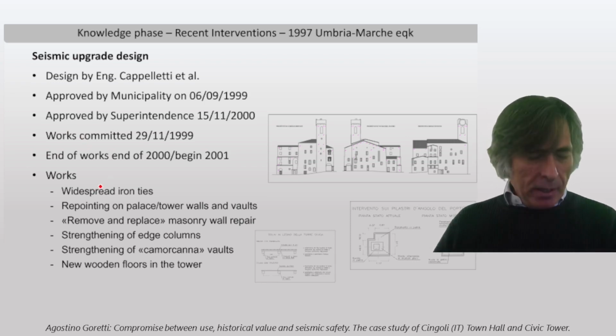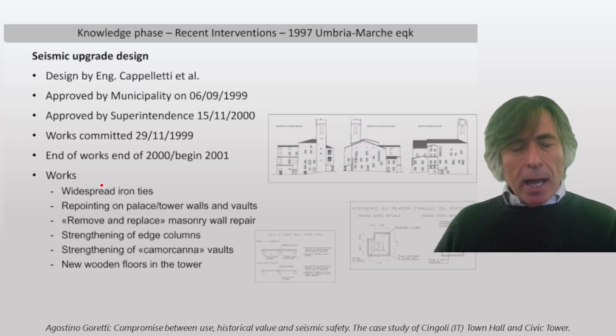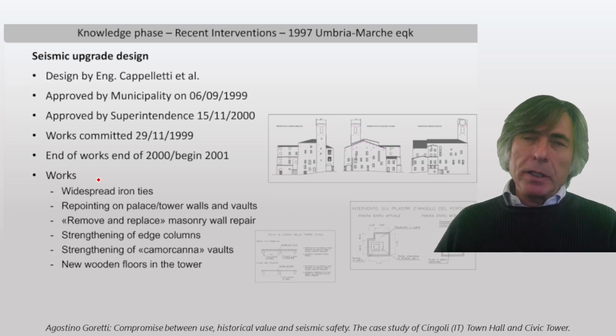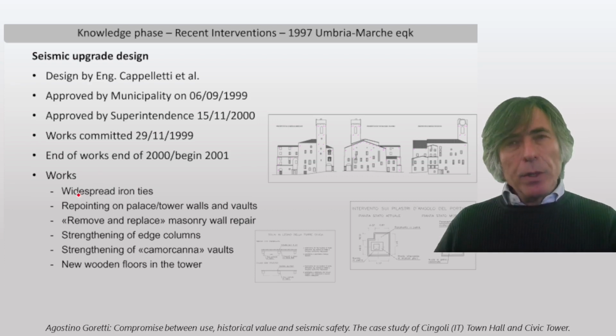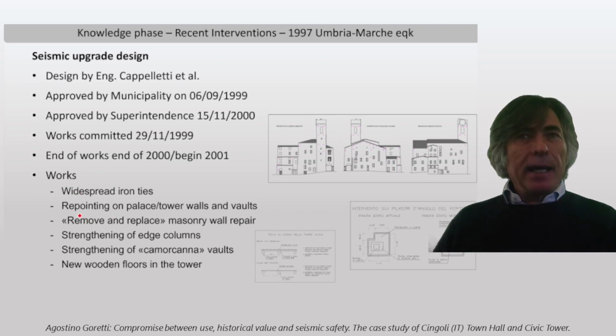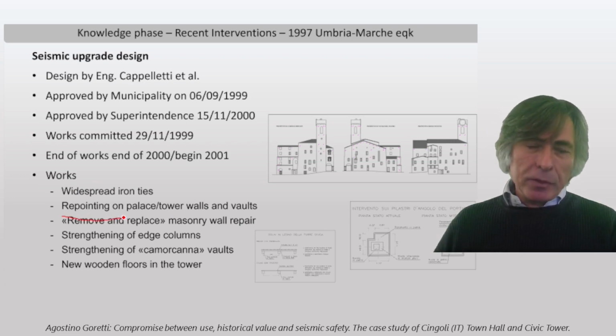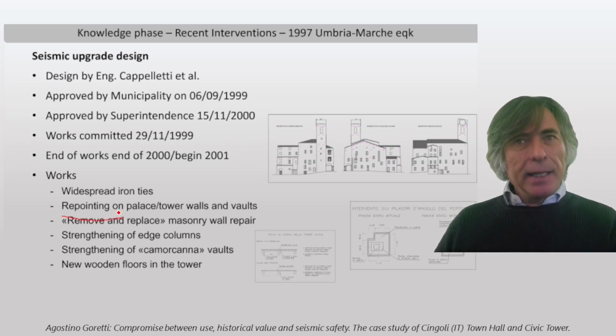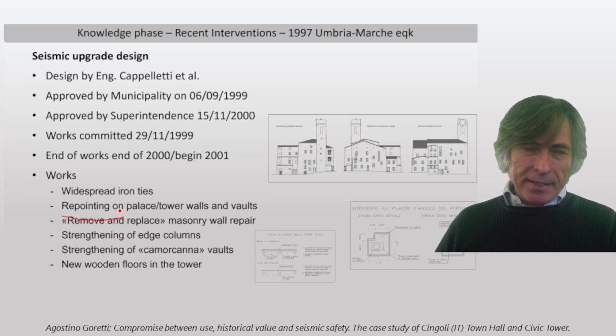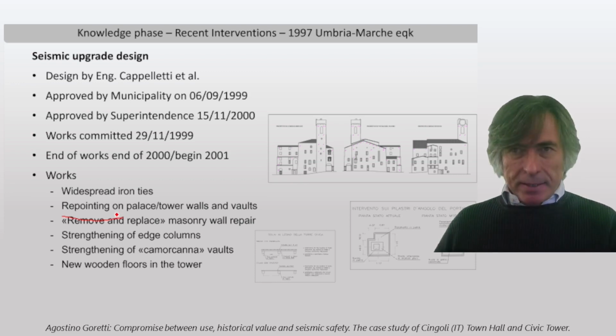At that time, it was very common to have some upgrade design with calculation only on the elements where you intervene, not with a global assessment. So we found in this design basically this type of works: repointing of the mortar beds, and this repointing is basically removing the mortar from the outside part of the bed joints and replacing it with new one. But it can be done just for several centimeters, and when you consider that the walls are maybe 2 meter walls or 1.5 meter walls, you understand that this intervention is, in percentage of the thickness, quite limited.